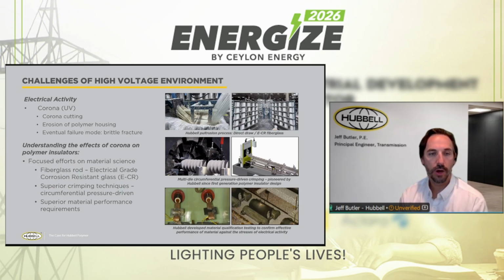It led to the focus on the performance of the insulator in those areas. For Hubbell, we had good performance with our insulators previously because of the design, and I'll talk about that a little later when I talk about our insulator design. But it did mean there was an increased understanding in the industry of the effects of electrical activity and corona for these polymer insulators. So there was an evolution in fiberglass rod, for example, where electrical grade was acceptable, but then everybody evolved into electrical grade corrosion resistant glass. It also led to the broader acceptance of a crimping technique referred to as circumferential crimping. This was a crimping technology that Hubbell helped pioneer back in the 70s, but the industry widely accepted it in the 90s. Today, almost every polymer insulator manufacturer is using circumferential crimping. And then it led to further advancement of materials, of polymer, of rod, of bonding, of molding of insulators.